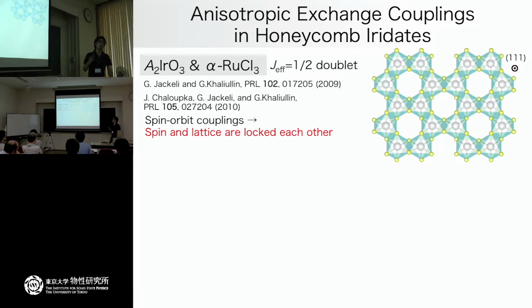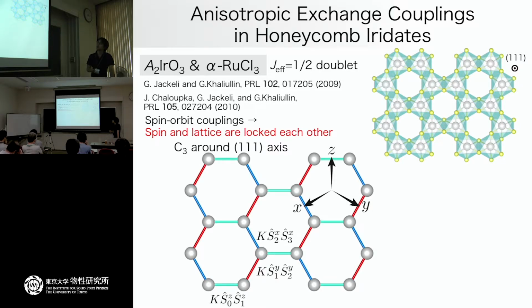But anyway, if you have spin-orbit coupling and a doublet on the honeycomb lattice structure, then there is some spin lattice locking. Here I show you the honeycomb lattice structure consisting of the iridium ions. Here, if you have spin-orbit coupling, then you may have bond-dependent interactions. Based on their prediction, this kind of bond-dependent Ising interaction becomes dominant in this system.